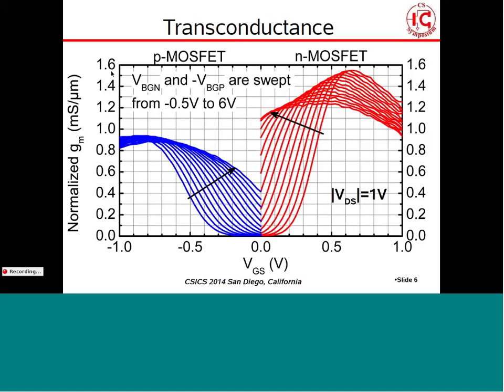Comparing with what we measured in LP-CMOS from the same foundry with the same transistor layout: the transconductance for the NMOS was the same — 1.5 millisiemens per micron — but for the PMOS it was worse in LP-CMOS. So we have a significant improvement in the PMOS, due to compressive strain induced by the bottom oxide layer in the thin-channel device, which improves the mobility of holes. In general, it's the PMOS that shows significantly improved performance over LP-CMOS technology.